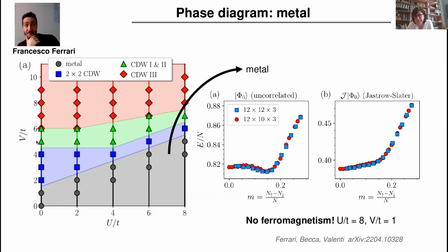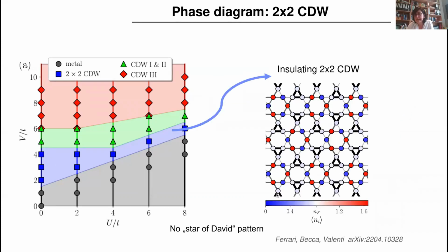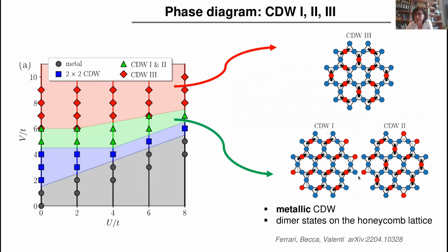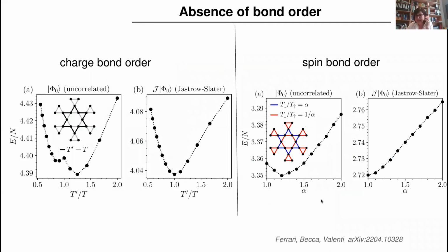Now, if we go to this region at finite V, this blue region is indeed a 2x2 charge density wave, but the pattern is not the Star of David pattern observed in experiments. Moreover, there are other phases of charge density waves as you go up into higher nearest-neighbor Coulomb repulsion, which are metallic types—these describe different kinds of dimer states on the honeycomb lattice. So what we have here is a phase diagram with charge density waves induced by electron correlations, but not the Star of David or inverse Star of David type.